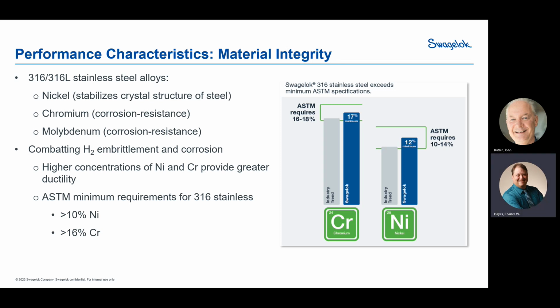Let's talk about something a little bit different and what makes up good material inside a fitting technology or valve technology that you're looking at within hydrogen. The ASTM standard for 316 material, and this includes 316L. 316L material is primarily used with controlled sulfur, controlled carbon to be able to allow for better welding and more consistent welding. If you have sulfurs that are different in one part you're welding to another part, it can cause the weld puddle to shift. So you want to control those well. That's what 316L is used for.